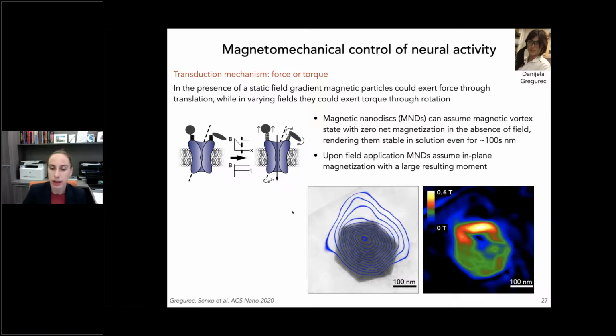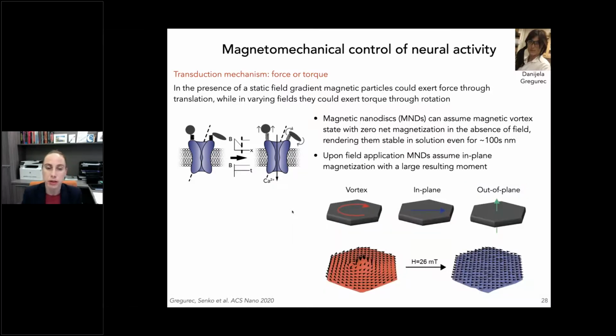When we take these anisotropic magnetic nanodisk particles and expose them to weak magnetic fields on the order of tens of millitesla, we can see a phase transition from a vortex state to an in-plane magnetization state. And when we have an in-plane magnetization state, we have a magnetic moment that is proportional to the volume of our particle. So now we have a lever with which we can pull on cell membranes.